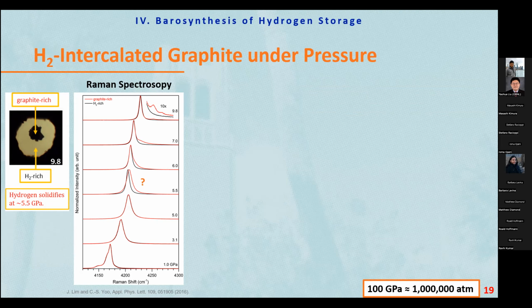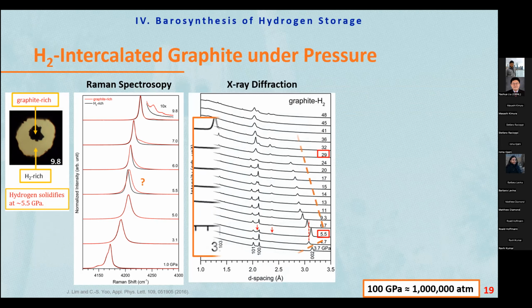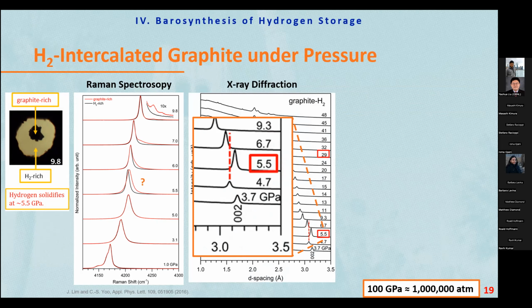We think they are the stored hydrogen in the graphite, different from the hydrogen outside. And to prove this idea further, we did X-ray diffraction measurement at WSU, and we found that indeed the lattice parameter of the C-axis increases rather than decreases under pressure. So right at 5.5 GPa, the lattice increases in the C-axis. So something goes into the graphitic layers, which is hydrogen in our case. And this proves that the hydrogen can be stored in the graphitic layer. This is the first evidence that we can use graphite as the hydrogen storage material.